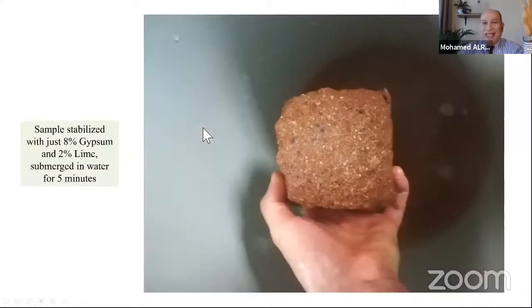On the other hand, this sample was stabilized with gypsum. We used 8% gypsum and 2% lime. After 5 minutes, it totally dissolved. So this is what I told you: gypsum is still not proven as a stabilizer. Maybe gypsum will increase the bearing capacity of the soil under dry compression only. In comparison to the non-stabilized samples, gypsum increased the bearing capacity from 25 kilograms per square centimeter to 45 kilograms per square centimeter. That's it, under just dry compressive strength. And we didn't reach more than 45 kilograms.